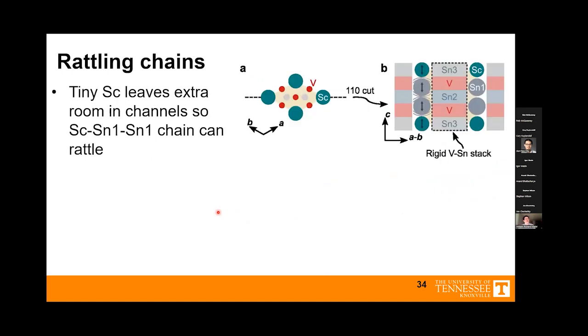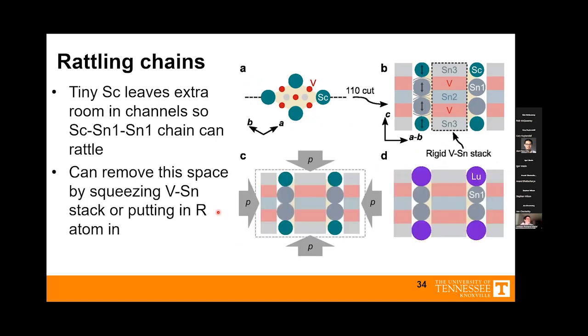Now, we've already shown that in the scandium atom, those atoms are rattling up and down quite a lot because this stack is rigid and they're loosely filling it. If we can remove that space by squeezing the crystal lattice, compressing that stack, or putting a bigger rare earth atom in and taking up that extra space, we can remove that charge density wave instability.